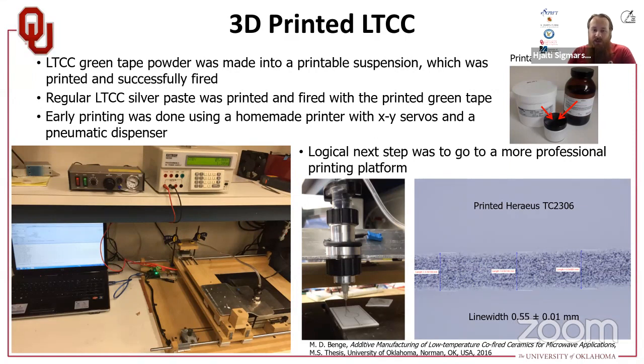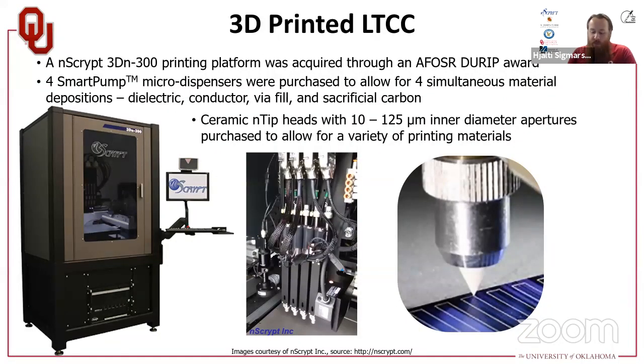We just used a pneumatic dispenser with some servos, and we created this little printer that we see here in the middle. We were able to print both the ceramic suspension, and on top of the ceramic suspension the conductor paste, and we fired it all together, and it actually came out quite nice. However, there are problems with the homemade printer: it's just really not good for high accuracy. We had okay accuracy, a repeatability of about 10 to 20 micrometers on these lines that we printed.